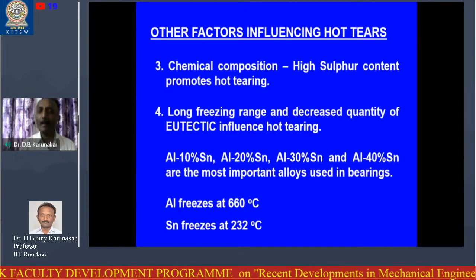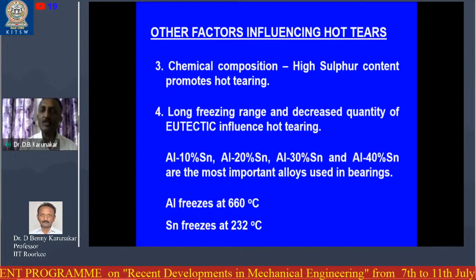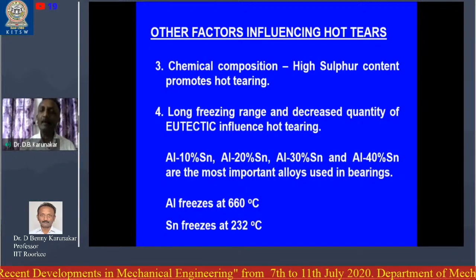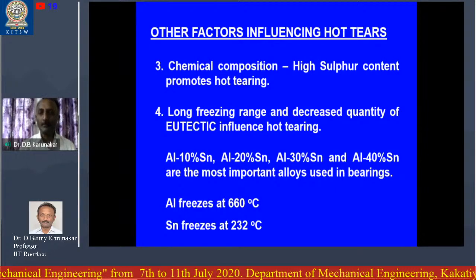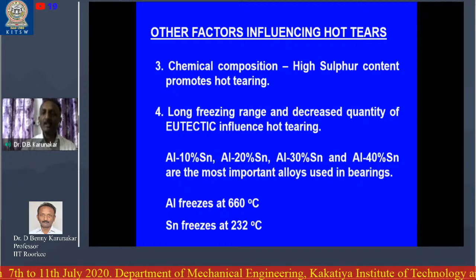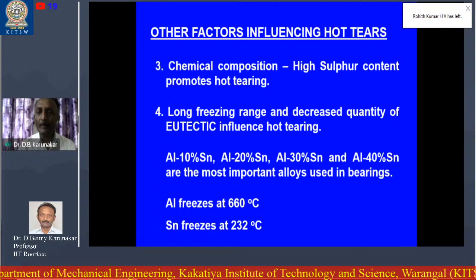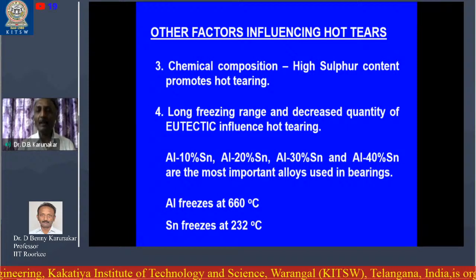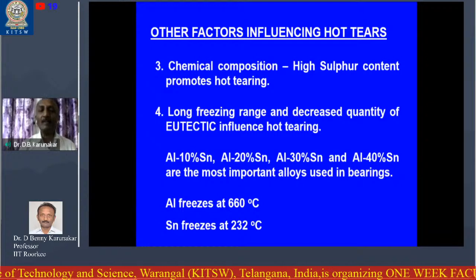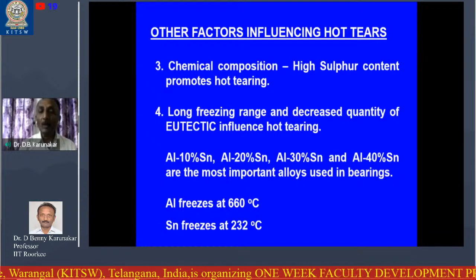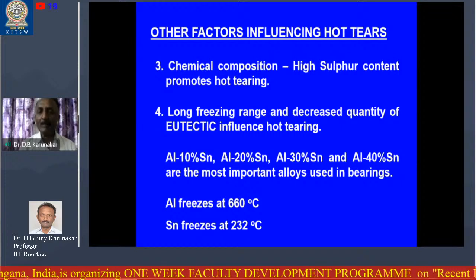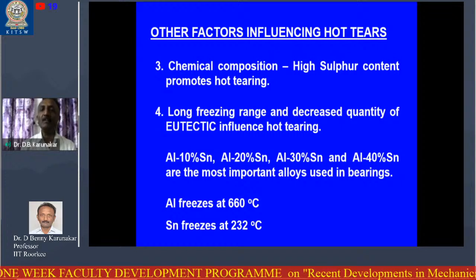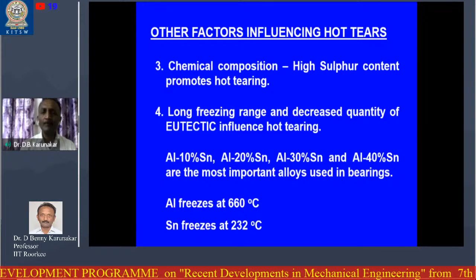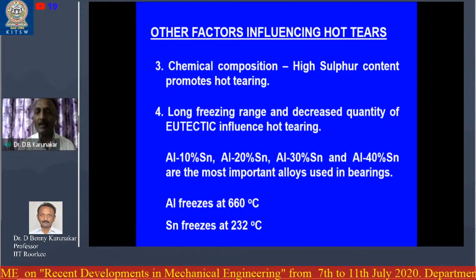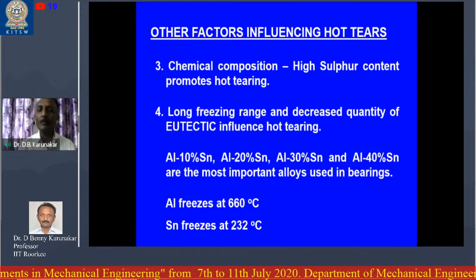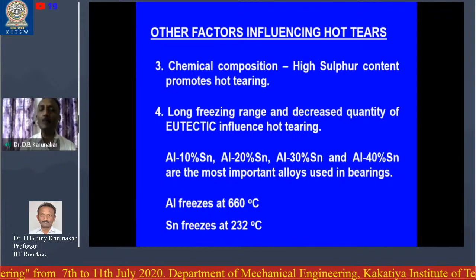Suppose you make a casting of composition aluminum 97% and tin 3%. Then what will happen? There is no doubt, initially the grains will be forming, aluminum grains and tin grains, but it won't be as in the case of aluminum 3% tin. So there is a local contraction there. Whereas when you use magnesium, where the freezing range is very, very small, the contraction will be there, but that is not local contraction, it will be a global contraction. So because of the global contraction, this hot tearing won't take place.